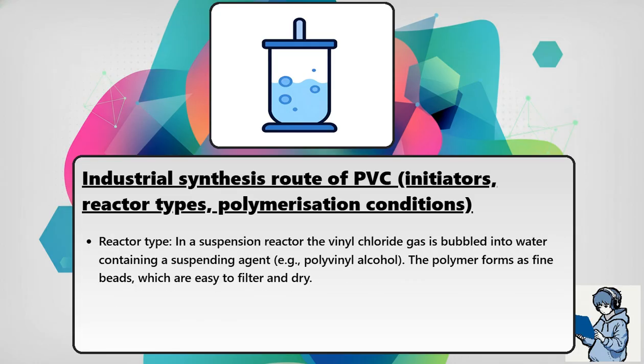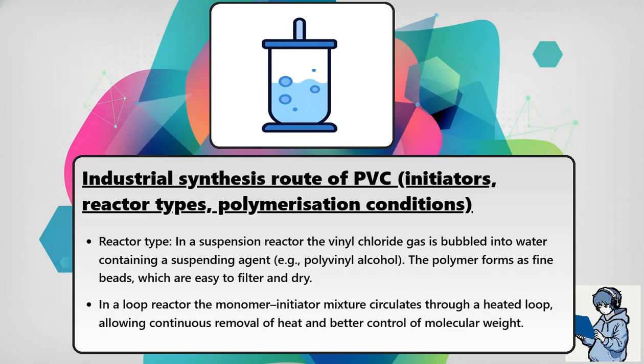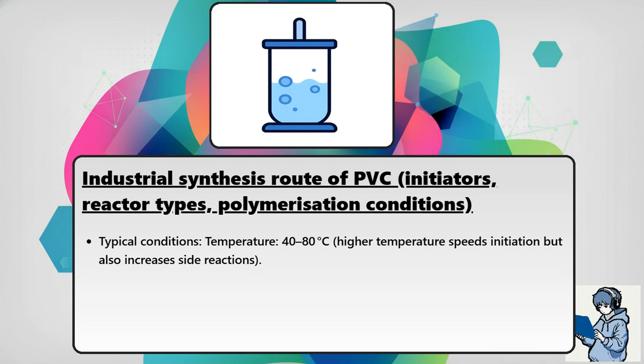Reactor type. In a suspension reactor, the vinyl chloride gas is bubbled into water containing a suspending agent, for example polyvinyl alcohol. The polymer forms as fine beads, which are easy to filter and dry. In a loop reactor, the monomer-initiator mixture circulates through a heated loop, allowing continuous removal of heat and better control of molecular weight.